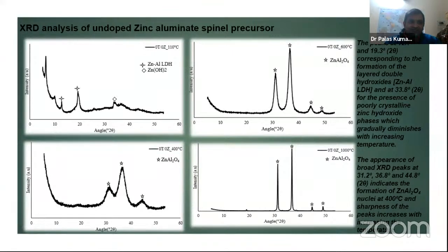So now, coming to the XRD analysis, the phase analysis of the precursor powder. Similarly, we took the sample heated at 110 degrees centigrade, 400, 600, and 1000 degrees centigrade, with three components mainly here. Quite interesting, at the lower temperature, especially 110 degrees centigrade, there are two peaks centered around 2 theta 12.7 and 19.3. These peaks correlate to the formation of zinc aluminum layered double hydroxide.